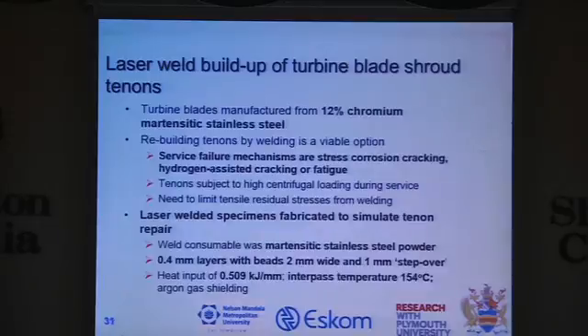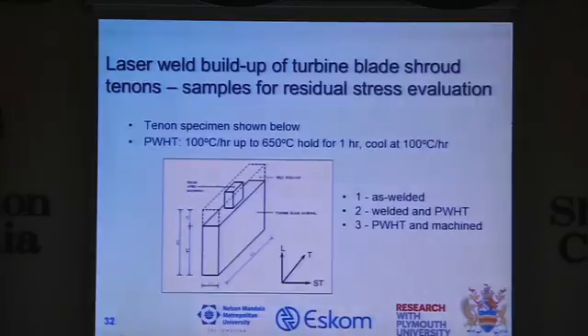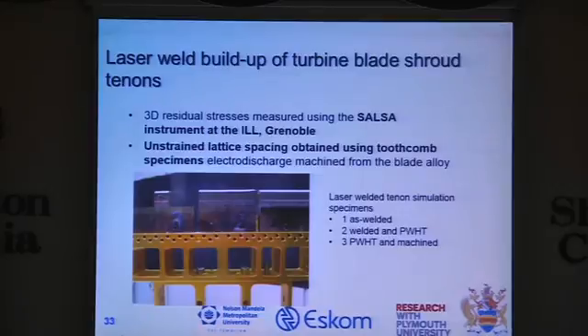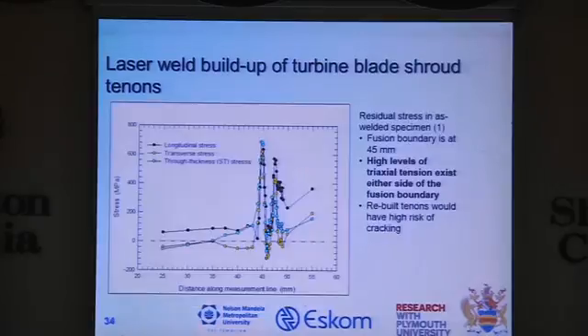What we've done in this case is, and that part you can read in the paper for the sake of time, it's just the laser welding specifications. We made a number of samples to take to the ILL. Laser welded tenons onto it. We had a sample as welded, one with post-weld heat treatment, and one with post-weld heat treatment and machining, and we quantified the residual stresses on that. You can just see the setup within the ILL.